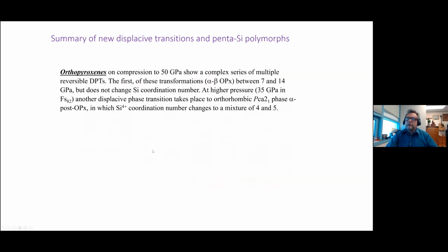So what we've learned about the behavior of these chain silicates at high pressure is that orthopyroxenes go through a number of structural phase changes that were not known before we conducted these experiments. On compression to 50 gigapascals, they show a complex series of multiple reversible displacive phase transitions. The first of these transformations, which happens depending on composition between 7 and 14 gigapascals, does not change silicon coordination number. It only affects the kinking of polyhedral chains of silicon.